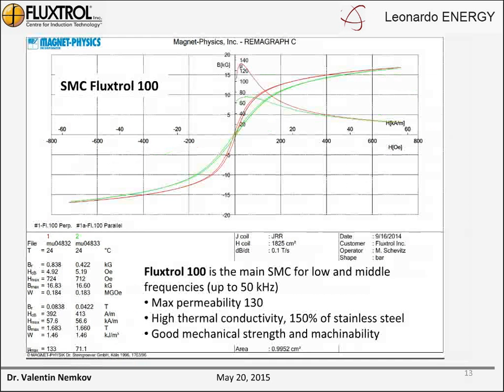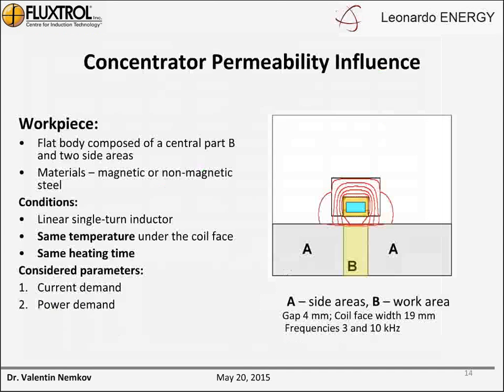The other material is a relatively low frequency material. It's Fluxtrol 100. We say that this material is designed for up to 20 kilohertz, but in some cases, with good cooling or not high magnetic loading, it could be used at upper frequencies up to 50 kilohertz. Maximum permeability of this material is 130. What's very important, it has high thermal conductivity, which is 50% higher than stainless steel. It has good mechanical strength and machinability.